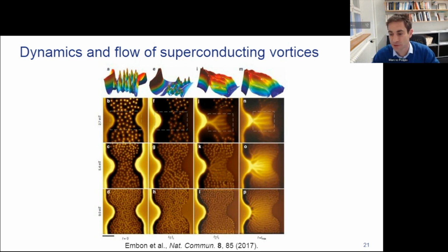So essentially, superconductivity is broken when one of those channels crosses all the way across the sample, and it turns out that each one of those channels corresponds to a step in the macroscopic transport that you measure, so in the effective resistance that you measure. In this paper, if you look it up, you can see a very nice correlation between the local imaging and the macroscopic transport, and I think there's a lot more that you can do in similar experiments on 2D materials, comparing the transport and the scanning probe measurements at the same time.